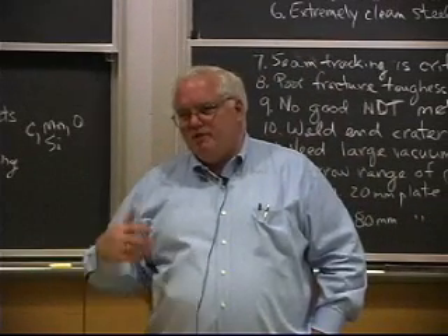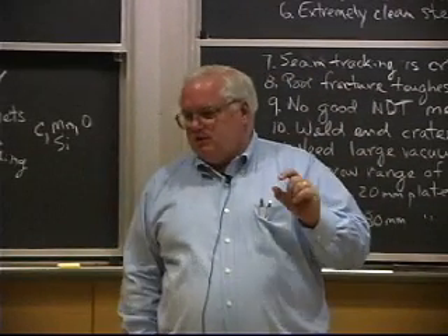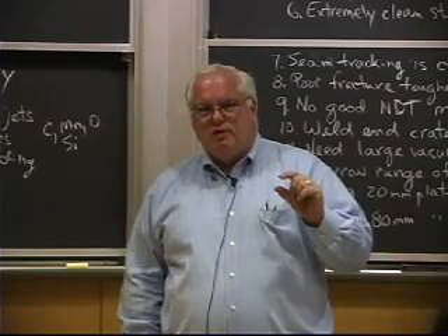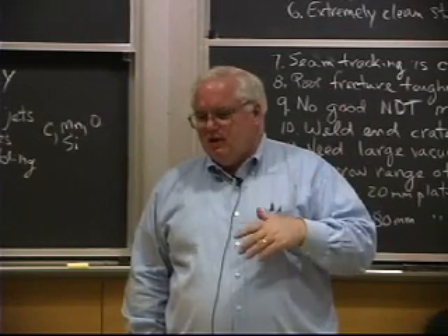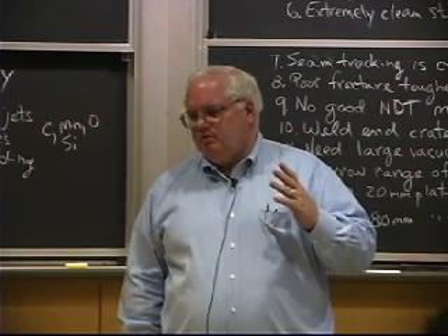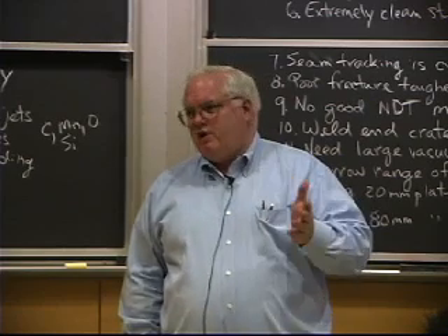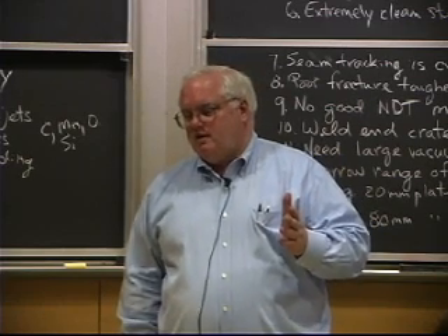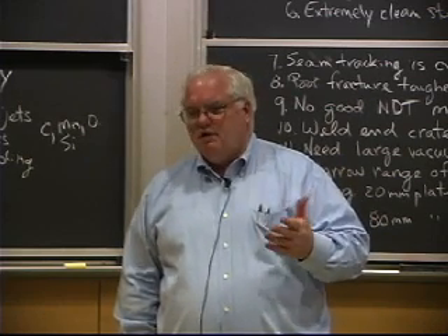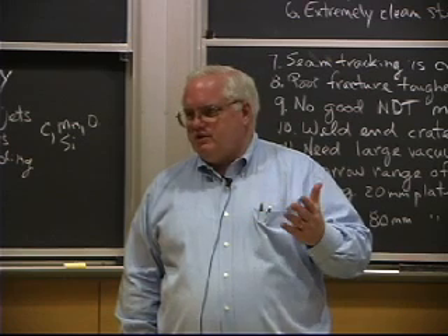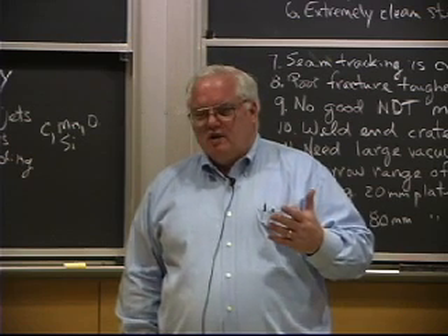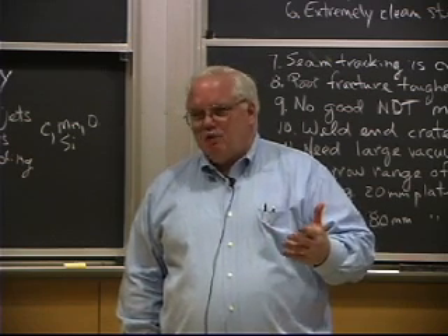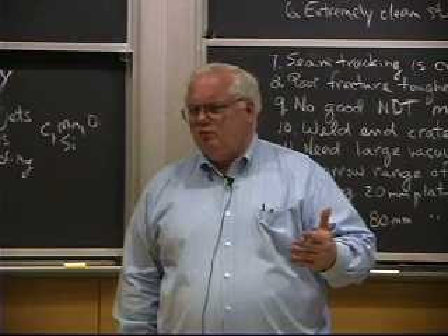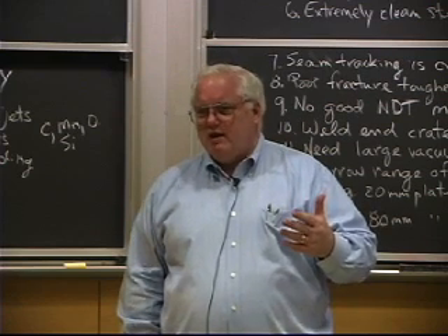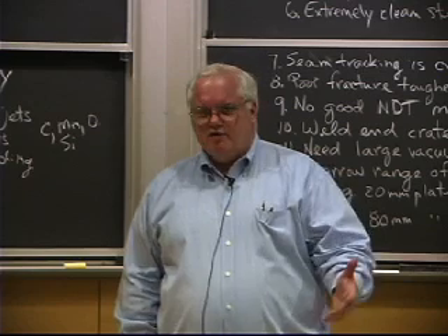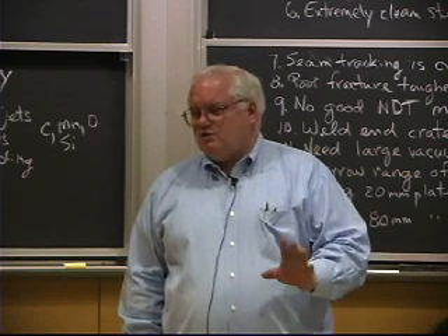In fact, I remember Professor Blue brought me this fatigue failure. He was a fracture expert here. And he had this fairly brittle fatigue crack from a bridge, and it was a weld, and the hardness was terrible. That's one of the reasons they had the fatigue crack, and it was brittle. And he had done the chemical analysis on the weld metal, and he had like 1% silicon and 2% manganese. He says, how did we ever get a weld metal like this? It wasn't because it was wet welded.